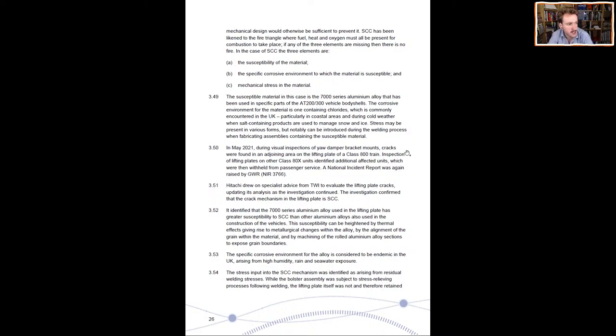During the visual inspections, cracks are found in the lifting plate. Inspection of those lifting plates identified additional affected units. They were then held back from service. So there we go. They confirm that the crack mechanism in the lifting plate is stress corrosion cracking.